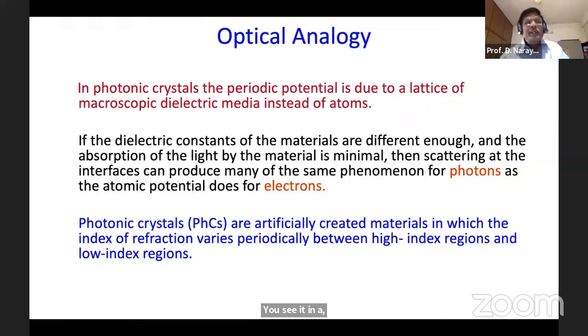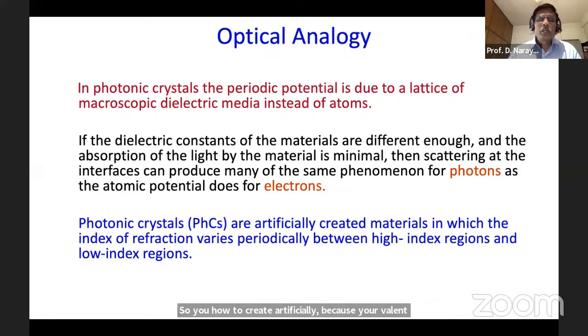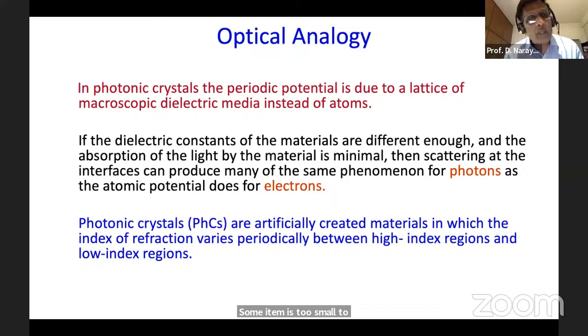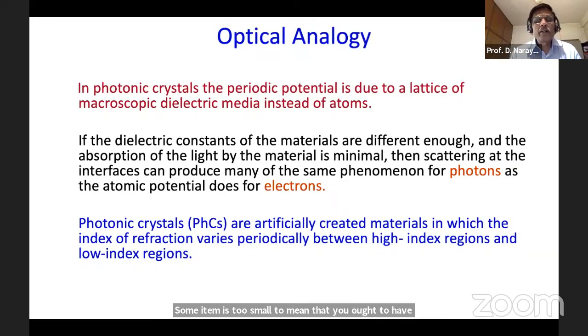So you have to create it artificially, because your wavelength is approximately 500 nanometers. That means there is no way that you can place atoms; an atom is too small. So you have to have spheres of the order of a couple of hundred nanometers, placed about a few hundred nanometers apart from each other.